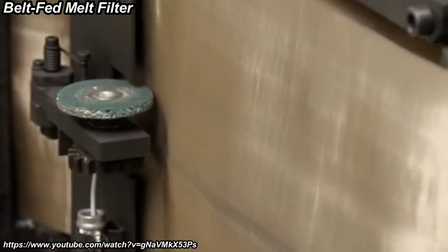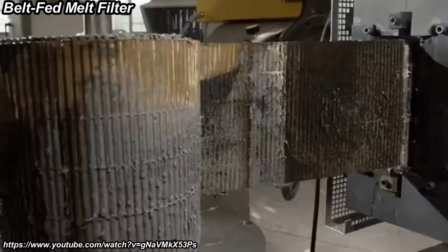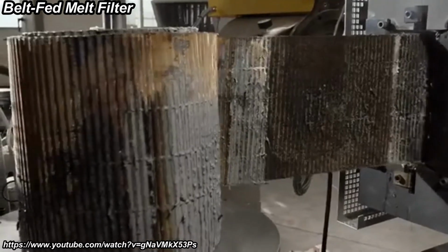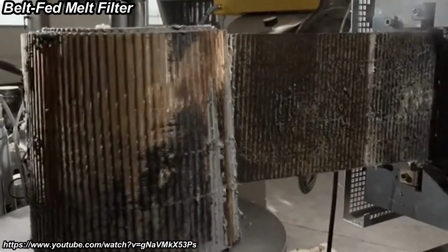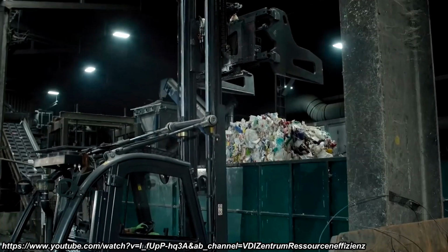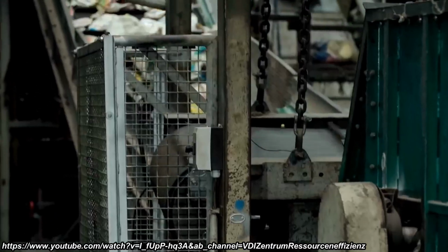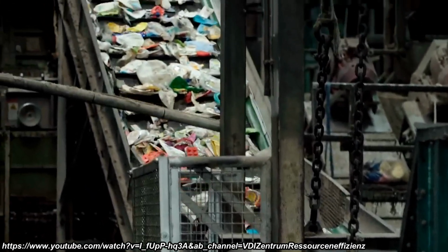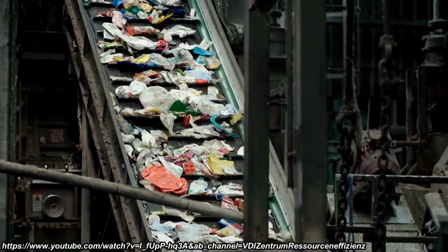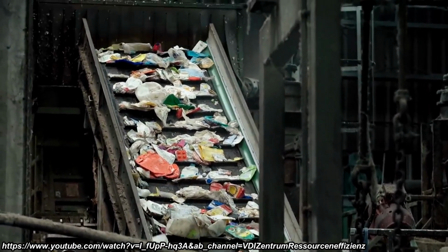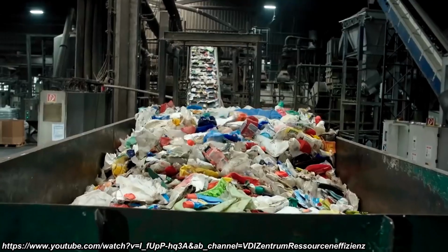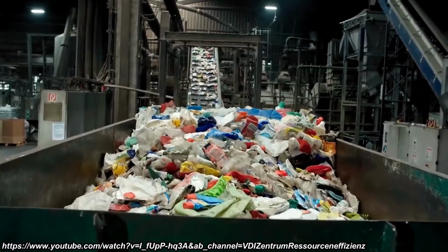The second type is the belt-fed melt filter. Instead of a rotating disc, this type of filter uses a large roll of metal mesh as the filter. Impurities in recycled plastics lead to discoloration, weaker material strength, and worse thermal properties. A melt filter can process virtually any thermoplastic polymer, and, depending on the mesh size of the filter, it can remove any impurity larger than around 35 microns wide.